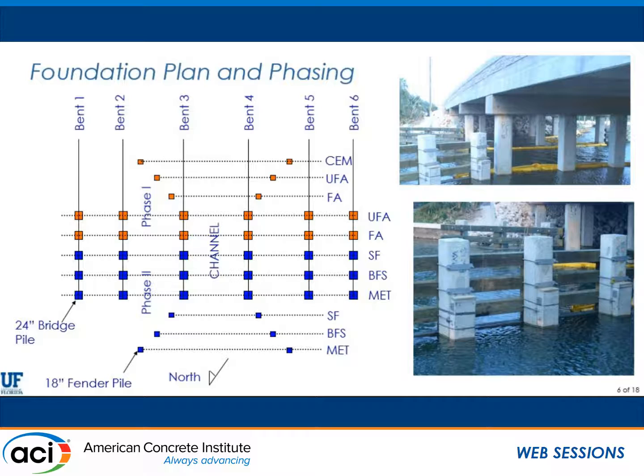The project was constructed in 2 phases, the orange and the blue there. Phase 1 was 2 sets of piles, and then the bents were divided up to accommodate the existing traffic there, and then the blue was the second phase. So the designations there, you see the CEM is all cement pile, and then we have ultrafine fly ash additions or replacements, just a straight up fly ash.